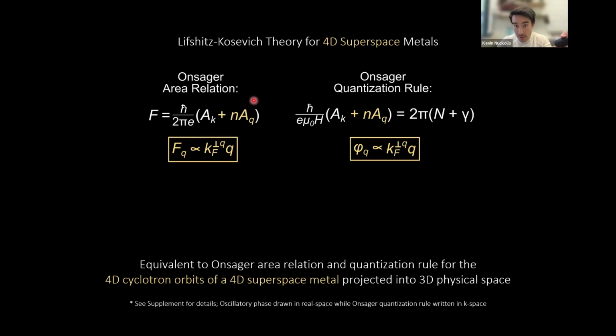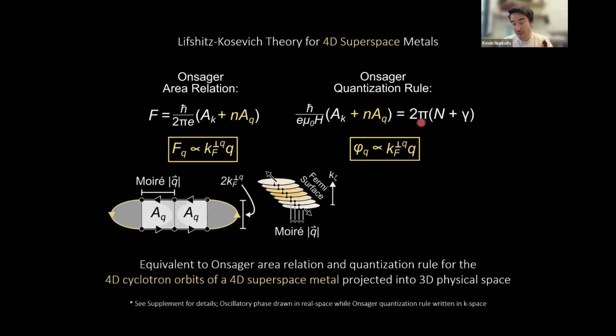And so effectively what we found in this mathematics is that there's an equivalent Onsager area relation and quantization rule that looks like a 4-dimensional cyclotron orbit in a 4-dimensional metal for some anomalous area that we need to motivate at this point. So there's some new total area that's producing this, although frequency is now proportional to area, and area produces 2 pi periodic cyclotron orbit. So graphically, we can take a lot of the construction from incommensurate lattices and try to figure out what that might look like in momentum space.